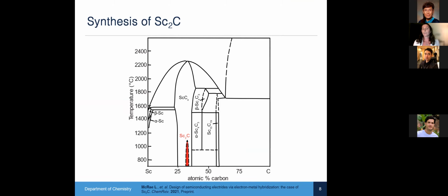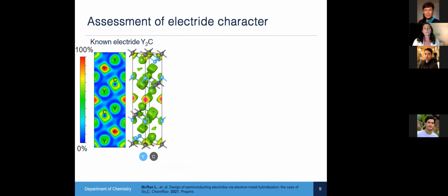And so given this information, we now wanted to understand the properties of this new structure. So we wanted to assess the electride character. We compare this to known electride diyttrium carbide, and you can see here what I'm showing is the electron localization function, which shows where the electrons are localized relative to other atoms in the crystal structure. And so you can see here that we can see electrons for both the yttrium and carbon atoms. We can also see electrons that are localized aside from those, and those are the electride sites.